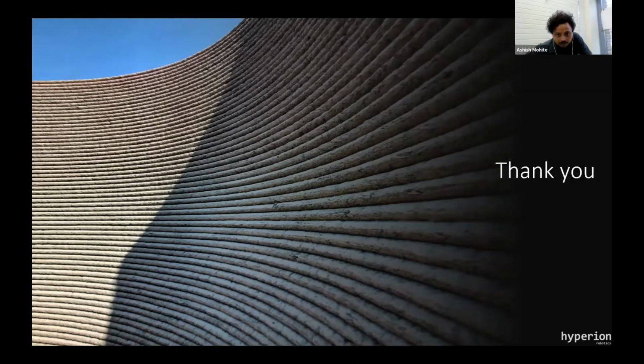How about stability of printed walls at larger dimensions? What is the largest size of aggregate that you use? So the largest size of aggregate which we use is, right now we have used 3 millimeter as the largest aggregate. So that's the largest dimension which we have used.